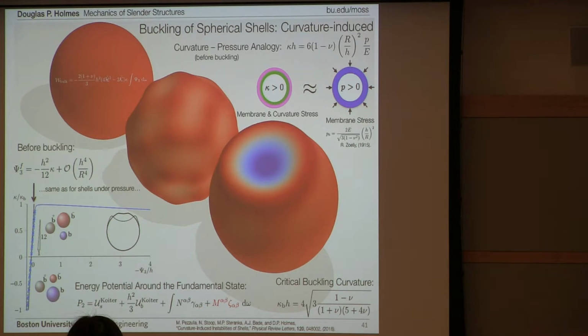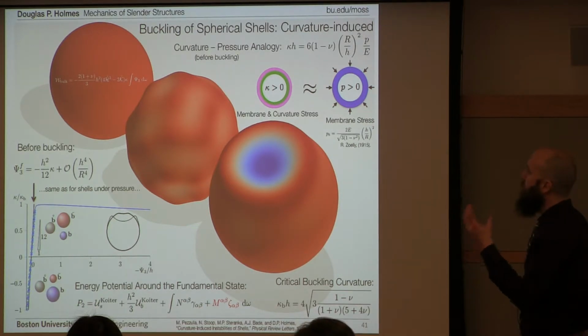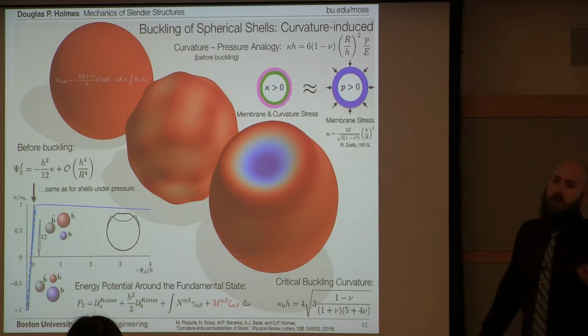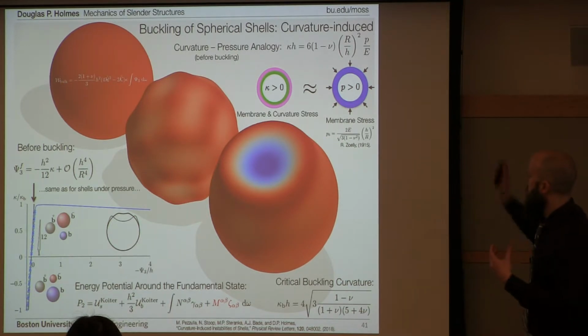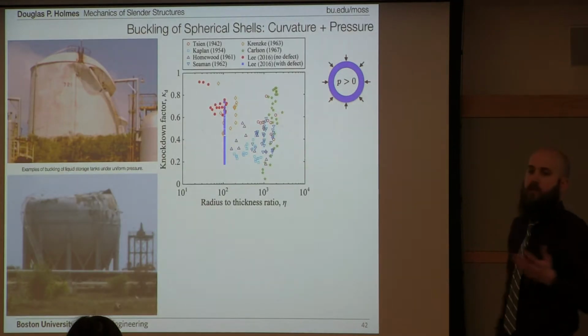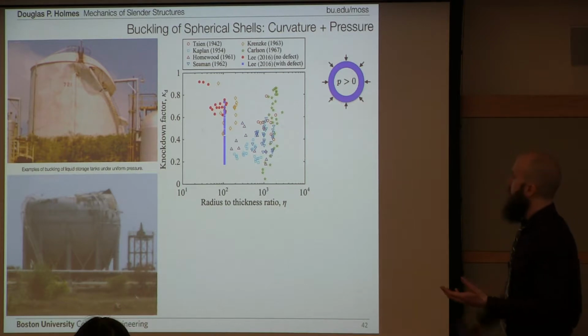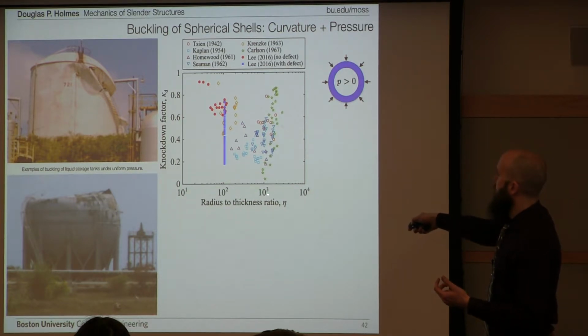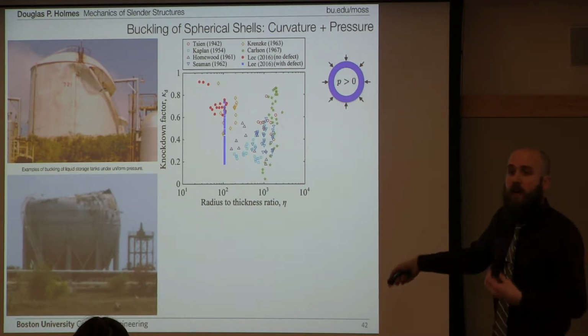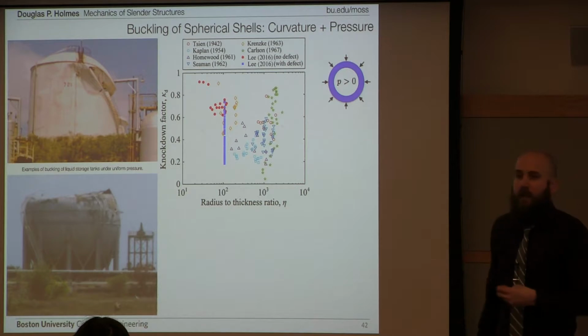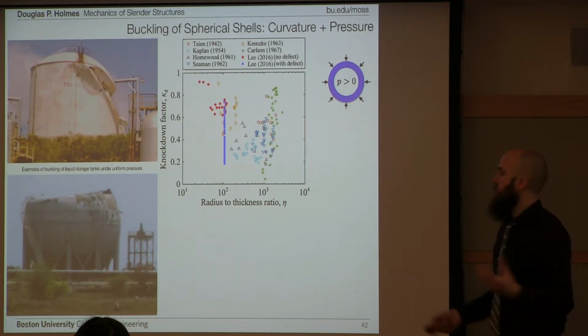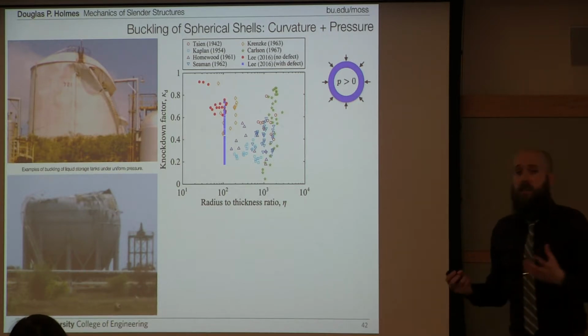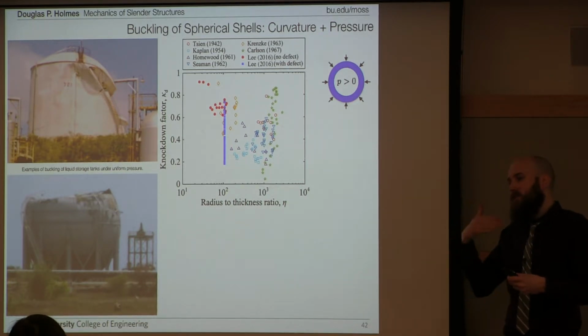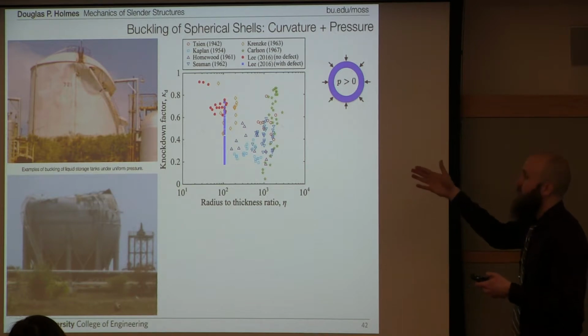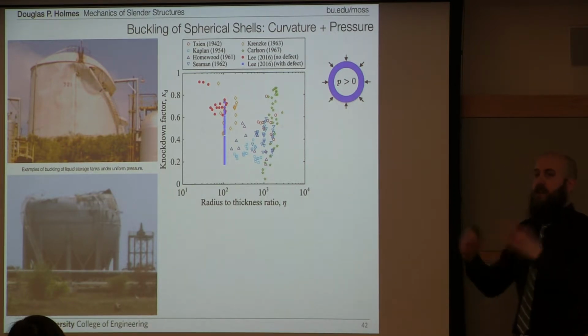Why does this matter? Well, shell buckling is probably one of the most frustrating problems in all of structural mechanics, because you write down this beautiful equation over 100 years ago, and you find out that it does an absolutely horrendous job at predicting when real-life structures buckle. Here is the ratio of the radius to the thickness of a shell, and if that equation did really well, all of these data points would be on this line. And they're clearly not, and there's no systematic way to predict what will happen. This is what's known as a knockdown factor. It basically is a fudge factor that says, oh, you're making a spherical shell, just overestimate how much this thing will buckle by maybe 20, 40, 80%, and we'll just put that in our calculations and then say, that's when this thing will buckle.